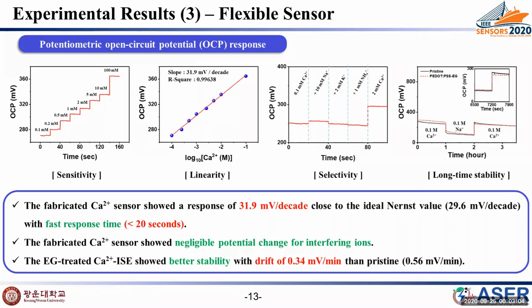Now, these 4 figures show the performance of the fabricated sensor. The experiments were performed with DI water containing different concentrations of calcium ions. The fabricated calcium ion sensor showed a linear response with a slope of 31.9 millivolt per decade in log scale. To confirm its selectivity against interfering ions, sodium, potassium, and ammonium ions, major components in biofluids, were chosen as electrolytes. The fabricated calcium ion sensor showed negligible potential change for interfering ions.